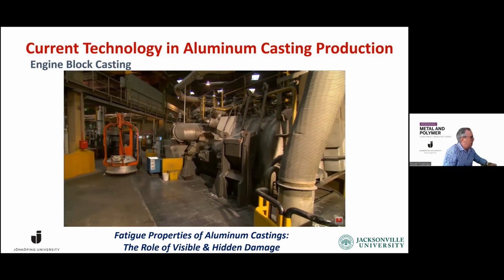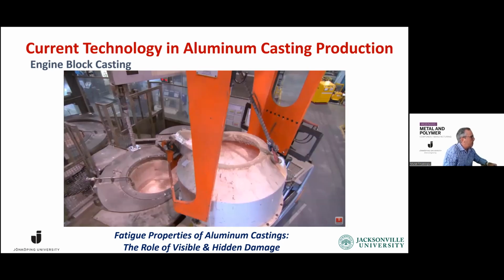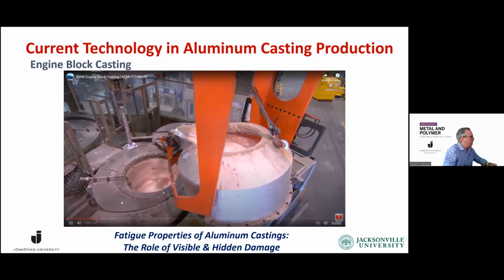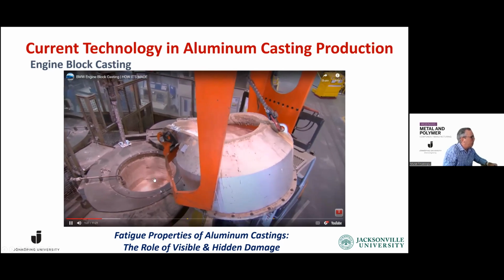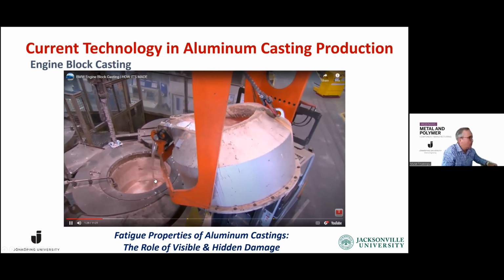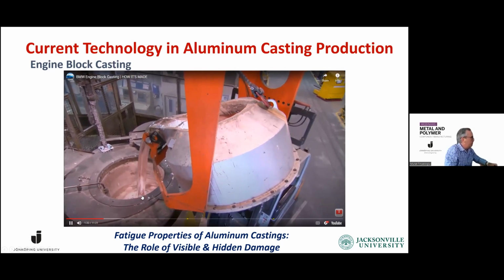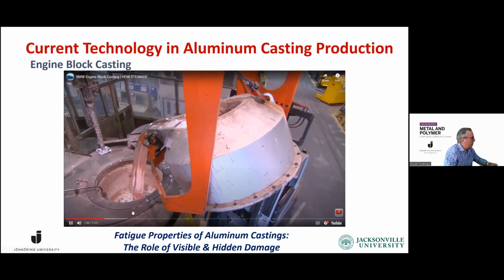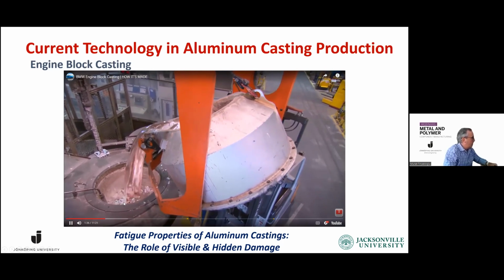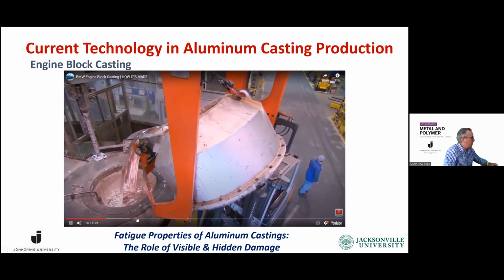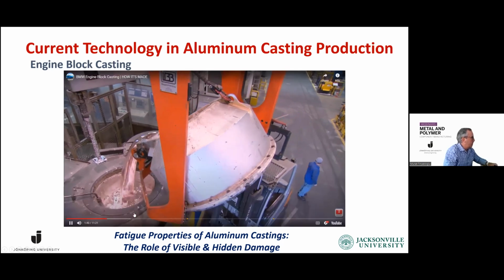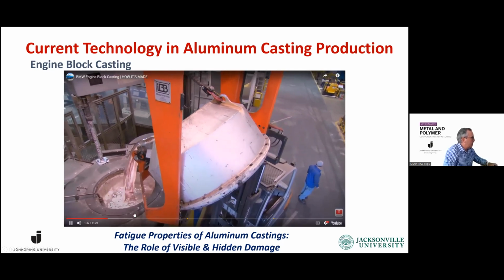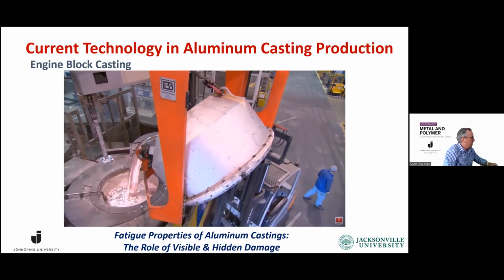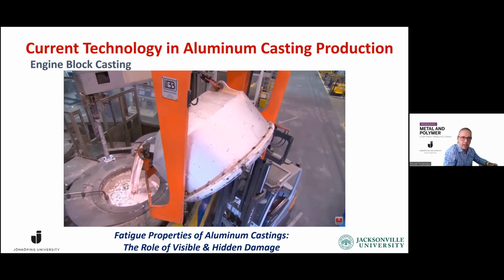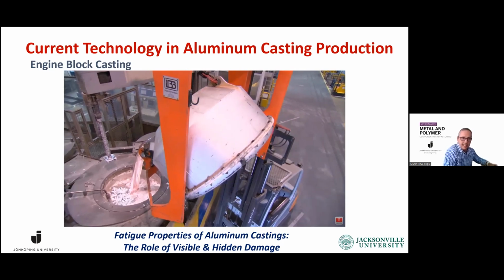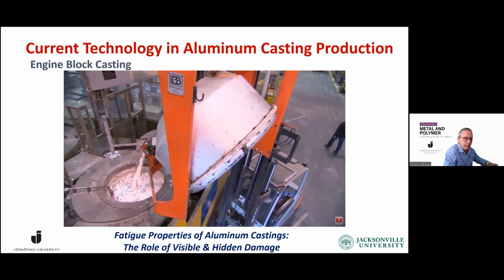It's taken to the casting furnace, and it's going to be poured just like we're pouring water from a distance, and you're going to see all the violent mixing of bubbles in the crucible, the lower crucible in the casting furnace. And this is a very highly damaging process. A lot of oxide is being entrained into the liquid metal.